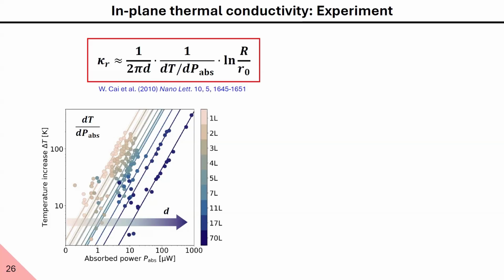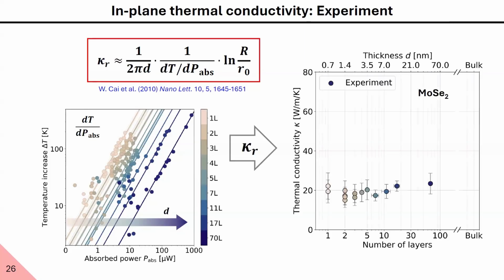And how does this relate to the thermal conductivity? Well, we only need to know the thickness of our flake, the radius of our hole, the size of our suspended region, and the radius of our laser spot size. We can now plot the in-plane thermal conductivity of these flakes, and we see that not much is happening with thickness, but it seems that it's going slightly up for thicker flakes. In any case, all our flakes are extremely thin, and importantly, down to the monolayer limit.